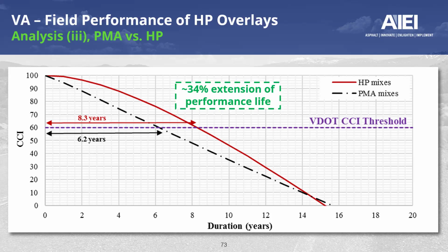Well, I'm going to put a caution here. While these numbers might look much lower compared to typical numbers that we see on overlays, I want to remind you that these are 1.5-inch or 2-inch overlays on top of a jointed concrete pavement that was not necessarily treated to the best prior to construction. So all these will factor in. And if we go with the rule of thumb of reflective cracking of 1 inch per year, I assume these numbers are pretty much high compared to what we typically see with reflective cracking on conventional overlays on top of jointed concrete pavements.